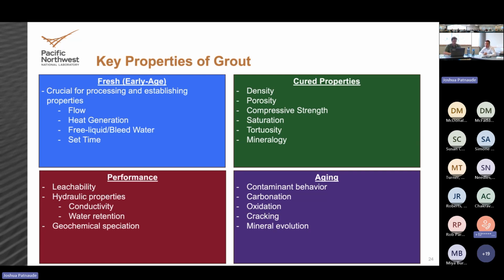Once that material starts to harden and gets to that set stage, because it's trying to react with as much water as it can, you can still have some free water. And if you're not smart with the way you design your material, you can end up with what's known as free liquids or bleed water. That's where you have a cured material and you end up with liquid sitting on top of it. Eventually, with most cements, that liquid will be reabsorbed and consumed just a couple days later.